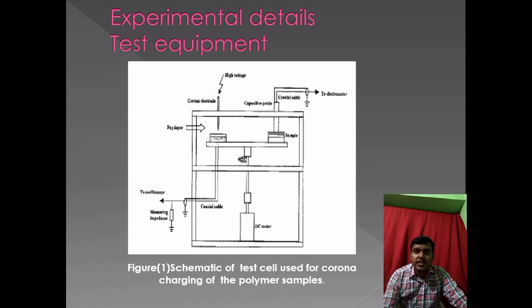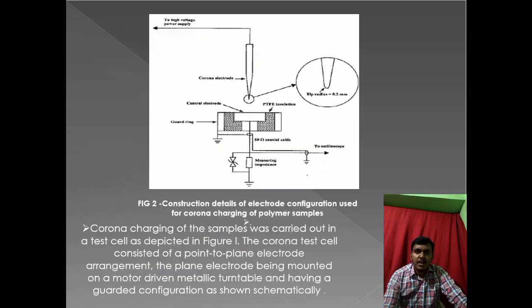Next, coming to the test equipment, figure 1 shows the test cell where corona charging of the samples was carried out. It consisted of a point to plane electrode arrangement, and the electrode configuration is shown in figure 2 in the next slide. The rounded tip of the point electrode has a radius of 0.2 mm, and during charging time the corona current was monitored with a CRO using an RC impedance as voltage transducer.